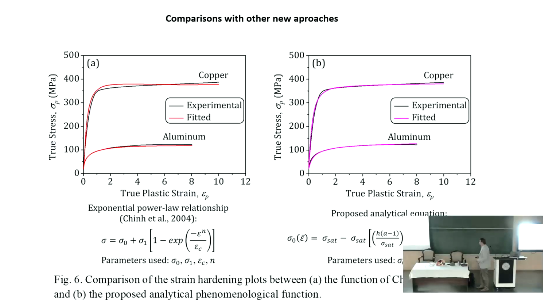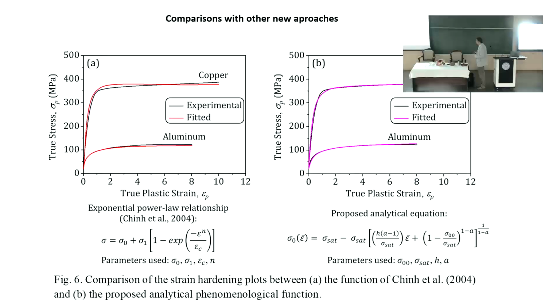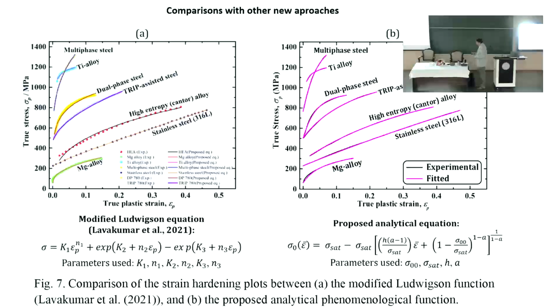That's no doubt about it. So with the same number of parameters, we get better agreement, and it does even more, because you can use it in crystal plasticity simulation. Another, it's an Indian work, Lavakumar et al., 2021. It was just published, and because it appeared in the same journal, we immediately checked whether our function is as good as that one. They made a huge work here. You see there is steel, titanium, dual-phase steel, TRIP, high entropy alloy, stainless steel, magnesium, all this they were doing. And pretty good agreements are obtained with their function.